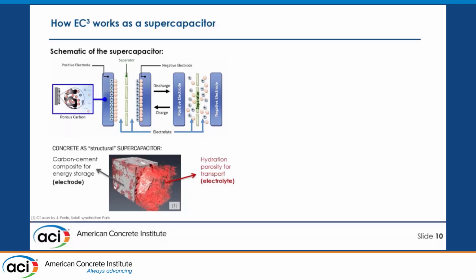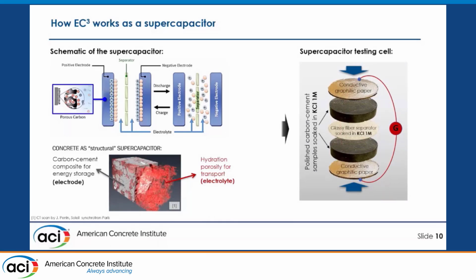The electrolyte is the medium that carries ions. In this assembly, the carbon cement composite plays the role of electrode, while hydration porosity serves for transport. And here is a CT image from Soleil Synchrotron Paris, which shows that more than 90% of hydration porosity is interconnected. So that gives us the possibility that ions can reach the nanocarbon particles. Here we can see our EC cube material, with two electrodes separated by a glassy fiber separator, and all soaked in electrolyte.